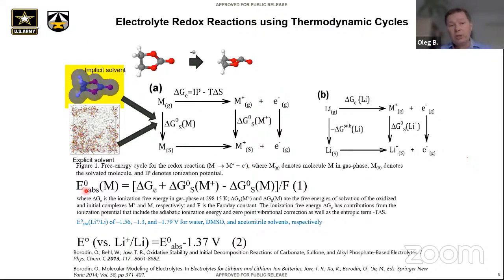So we can get the absolute potential. However, what we're interested in is not the absolute oxidation potential, but the potential versus lithium. So we're going to do the same as lithium goes from lithium metal, sublimates in the gas phase, and then becomes a lithium ion. It's best to just use the experimental value to complete the cycle. When we couple two of these thermodynamic cycles, we come to a very simple expression: we have a correction factor of about 1.37 or 1.4 from the absolute oxidation potential.